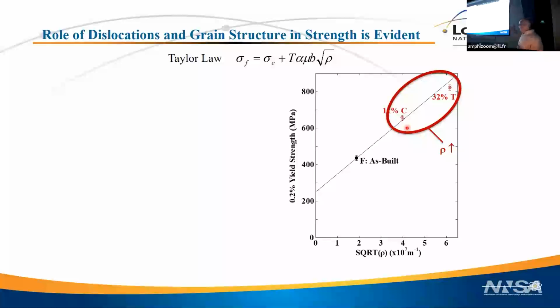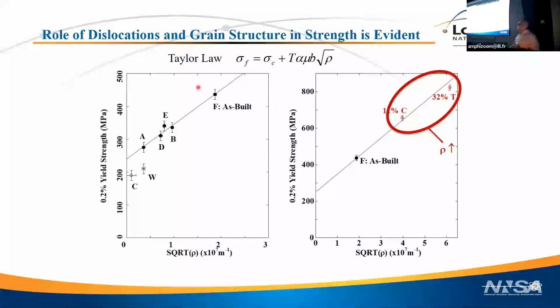So the fact that you get a nice line there gives you some confidence. And this is the same line as the one on the right, just on a different scale. But if you extend that same line down to all the heat-treated samples, you see how they continue to fall on that line as the dislocation density drops, and then sample C is the one that recrystallized.